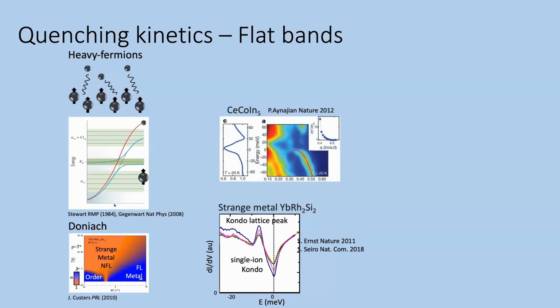And let me also show you a result on cerium cobalt indium 5 that was discussed yesterday by Laura, where again, you can see it's tilted sideways, but you see the peak-dip structure around the Fermi level, and also in the quasi-particle interference, which is STM's way to image dispersion. You see that there's a band that flattens out towards the Fermi level, and this is the hybridized light band that hybridizes with the heavy band, forming the heavy fermion behavior in this material. Or that was the claim in this paper.